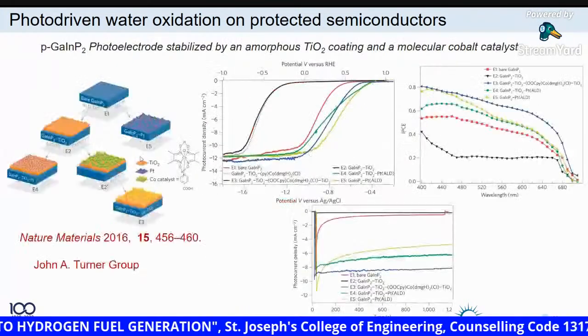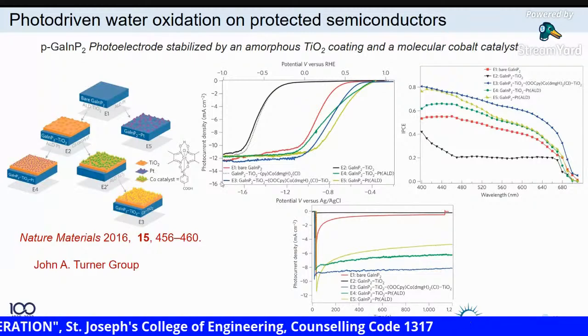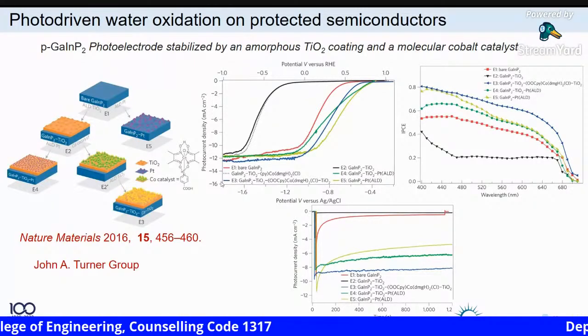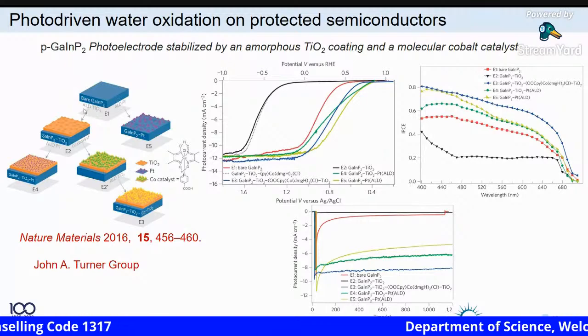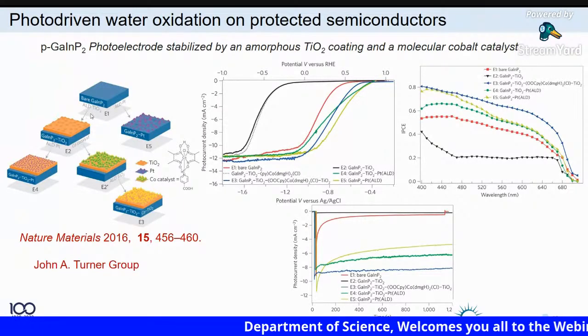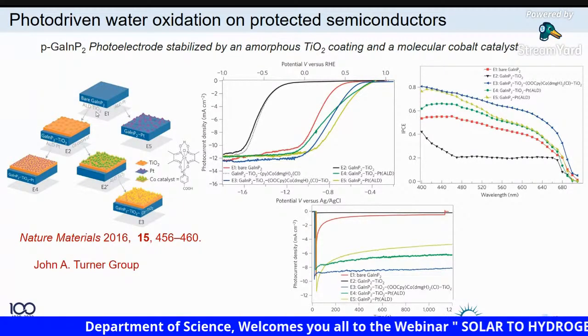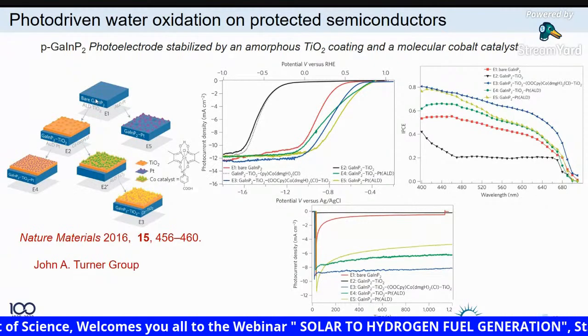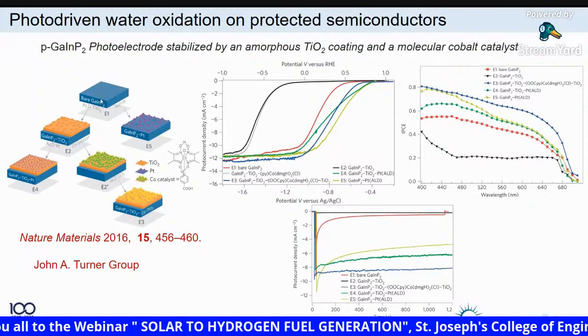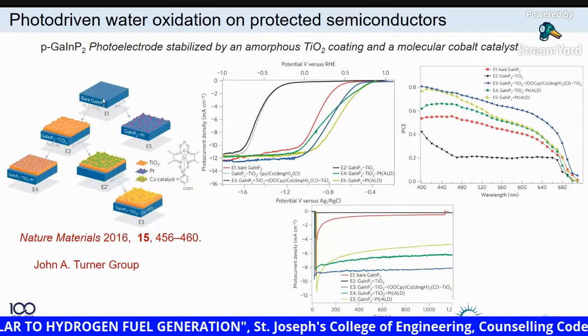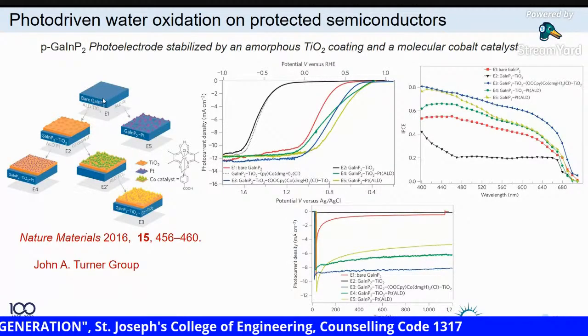So I would like to compare a recent report by Professor Turner's group. They coated by ALD, that means atomic layer deposition, a very thin titanium dioxide layer on the well-known p-type gallium indium phosphide. Gallium indium phosphide is highly corrosive if you put it in water under long light irradiation.